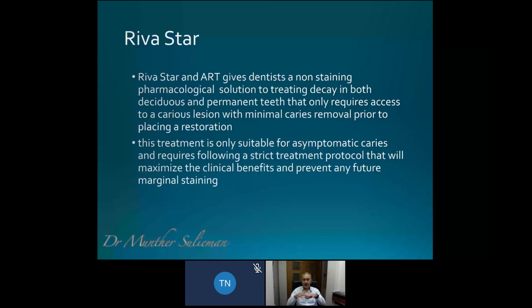You're cleaning out at the edges of the cavity, and the mushy decay that you see can be quite mushy, and you're using it in these sort of circumstances. You basically use a probe just to agitate it and flick off any loose bits. Then you etch the whole cavity. When you etch with phosphoric acid, you etch it for 10-15 seconds, then you wash it all out, then you apply the silver, and then you immediately apply the potassium iodide, and then you wash the cavity, and then you will place your glass ionomer on top.